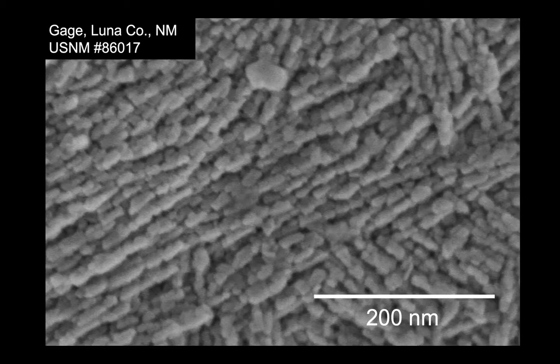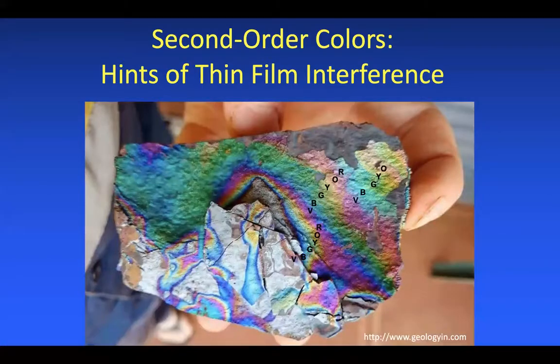So my first reaction was, okay, we've got a diffraction grating here. We see these kinds of parallel lineations. But then I looked at the scale bar and I realized that the spacing between these lineations was far too small to account for any kind of iridescence. It's on the order of 20 nanometers or so, and that's much too small to create an interference grating for visible light. So I had to think about other possibilities.